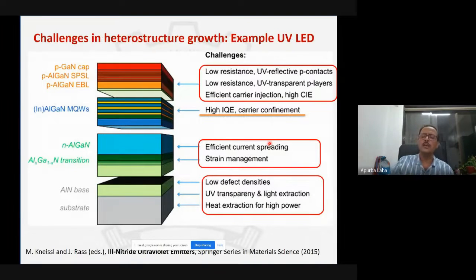And now coming to the real device structure. This is an example of a UV LED, but essentially the primary emitter in the LED bulb that you buy will have a similar structure. You have a substrate, and you have the base, aluminum nitride. By the way, the substrate we use particularly for LEDs is sapphire, because it is transparent and that will give you the light emission as well if you want back emission. So the aluminum nitride here plays a very, very important role. In fact, I will show you that the introduction of aluminum nitride led to the Nobel Prize at the end. I'll talk about that story as well.